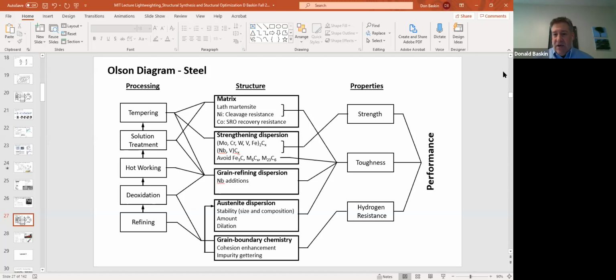You can increase the toughness, the fracture toughness of a steel by adjusting the chemistry such that when you quench it, not all the austenite goes away. Some of it stays there. And then because the austenite is only metastable, when a crack hits it, the energy from that crack can cause it to transform to martensite. And then there's a volume expansion associated with that transformation from the austenite to the martensite. And that can effectively clamp or reduce the stress concentration of a crack tip, which results in toughness. So that's the property section.